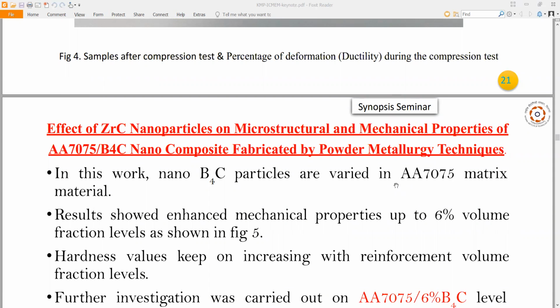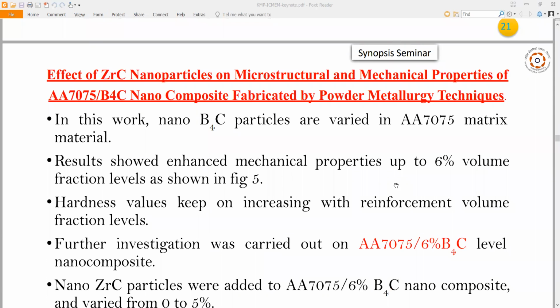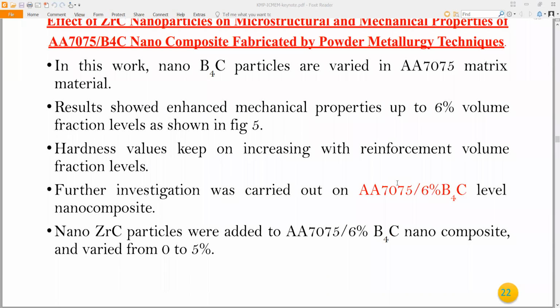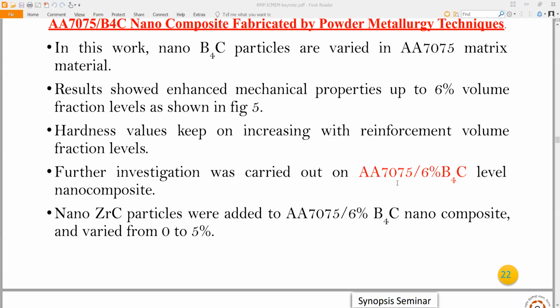Next, we studied the effect of ZrC nanoparticles on microstructural and mechanical properties of A7075 B4C nanocomposite fabricated by powder metallurgy technique. In this work, nano B4C particles are varied in the A7075 matrix material. Results showed enhanced mechanical properties up to 6% volume fraction level, as shown in figure 5. Thirdly, hardness value keeps on increasing with reinforcement volume fraction level. Further investigation was carried out on A7075 6% B4C level in the composite. Nano ZrC particles were added to the A7075 6% B4C nanocomposite and varied from 0 to 5%.